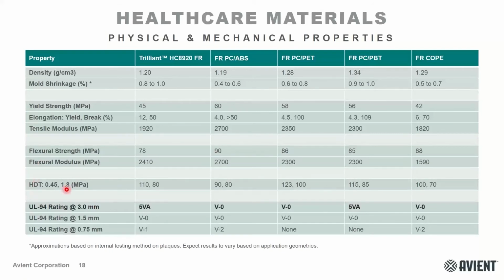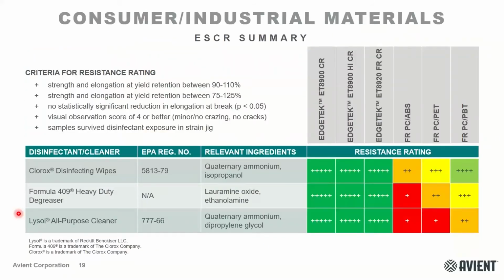same ballpark. The heat performance, HDT at 0.45 and 1.8 megapascals, is also quite comparable, falling somewhere in between a PCPBT and a PCABS. And the last thing that's also important to note here is the UL94 rating. So when we tested these internally, we were able to achieve a 5VA at 3 millimeters, V0 down to 1.5, and a V1 at 0.75. So these formulations do not have a tendency to drip, which can be a very difficult problem to solve. One other thing I'd like to note is that the flame retardant system for our Trilliant and Edgetek materials is completely halogen-free.